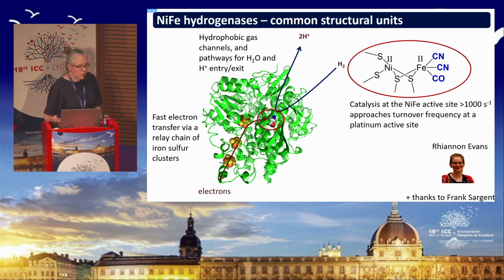So the enzymes responsible for biological hydrogen activation have either an iron or a nickel-iron catalytic site, and we're particularly interested in the nickel-iron enzymes because they tend to be more robust towards oxygen and hence more applicable for biotechnology purposes. And the catalytic site of these enzymes is built from a nickel and iron in this bimetallic active site that's deeply buried within the protein. And you'll notice that it has biologically unusual carbon monoxide and cyanide ligands that we rarely find in biology, but they are critical here to tuning the active site to turn it into a good catalyst for hydrogen activation.